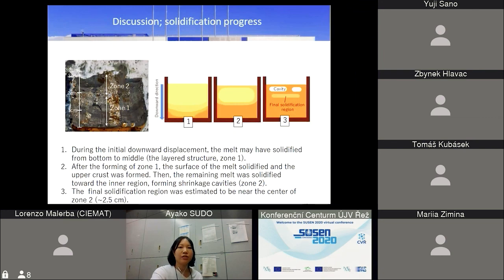Next is a discussion about the solidification progress of the melt. During the initial downward displacement, the melt may have solidified from bottom to middle, and the layered structure zone 1 was formed. After that, the surface of the melt solidified and the upper crust was formed. Then the remaining melt was solidified toward the inner region, forming shrinkage cavities, and zone 2 was formed. It means the final solidification region was estimated to be near the center of zone 2, about 2.5 centimeters from bottom of the ingot, near here.